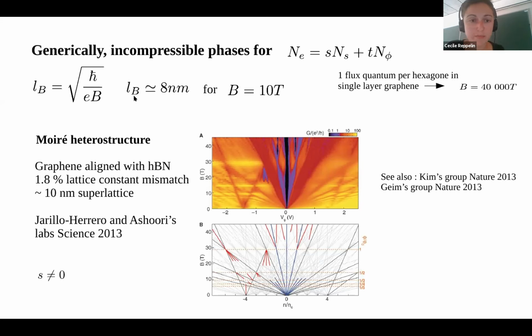So here I'm showing some experimental data where this phenomenon was observed and explored. The data here comes from graphene aligned with a substrate of hexagonal boron nitride. Both graphene and hBN are hexagonal, and they have almost the same lattice constant, but not quite. There's a very small 1.8% mismatch between the two lattice constants. And when you align those two lattices, this creates the moiré superlattice with the largest possible unit cell, which will be around, or maybe a little bit more than, 10 nanometers.